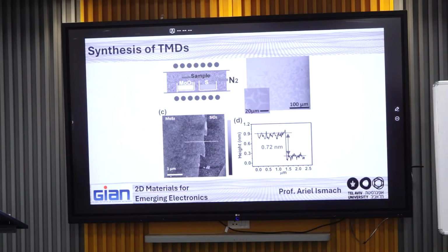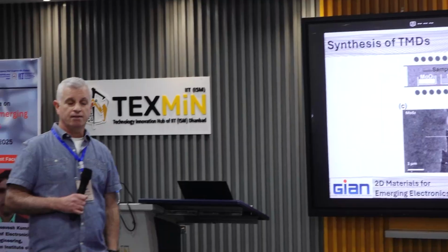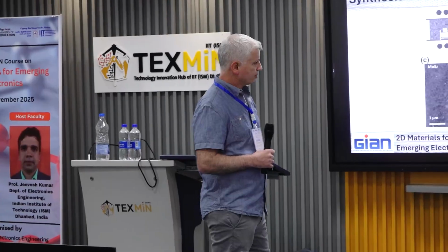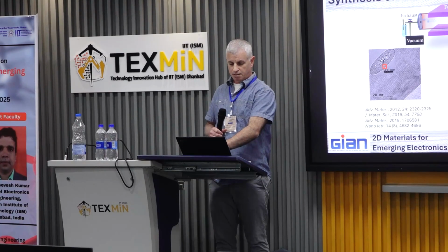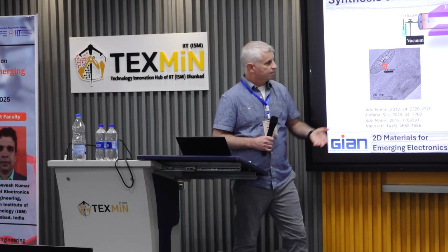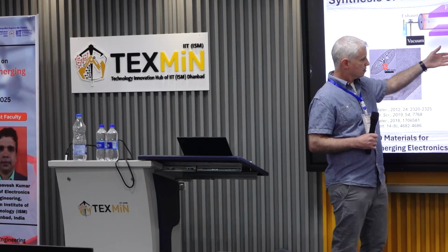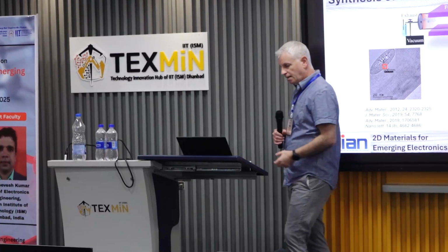And that's a problem, right? Because in contrast to the typical CVD processes in which you deliver the gas from the outside, in this case you need to put it inside the reactor. And the problem with that is that we have very little control over the flux of the metal to the reaction. And therefore, it has a lot of problems, as you will see in the next slides. So here, for example, you can see again CVD with the same metal oxide, molybdenum oxide or tungsten oxide.